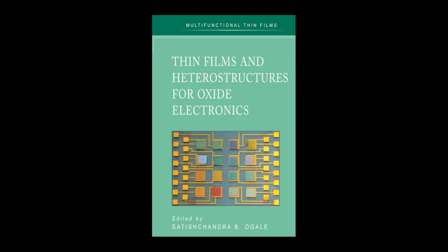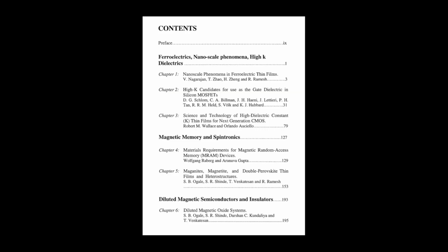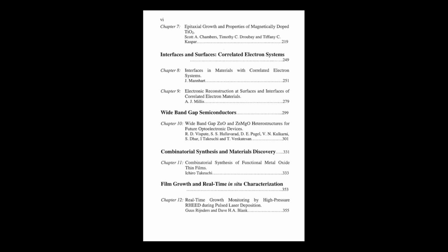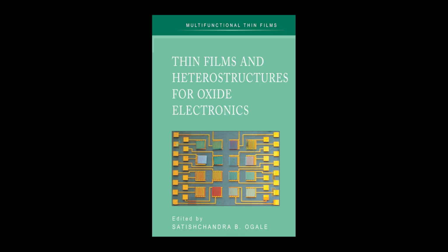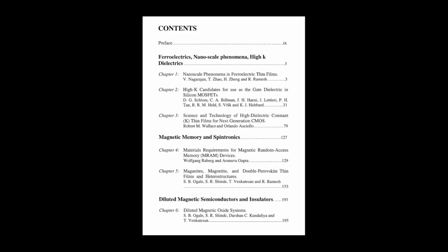And the material stepping up in the source is bismuth ferrite, BiFeO3, BFO. BFO looks really promising. It kind of nails the performance trade-offs. Its ferroelectric Curie temperature is incredibly high, like 800 degrees C. So it's stable way above any normal operating temp. And the performance metrics. Polarization. Massive spontaneous polarization, 90 microcoulombs per square centimeter. That gives you a really strong, clear memory state.